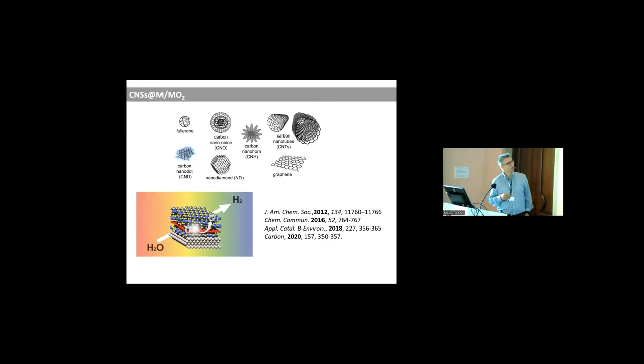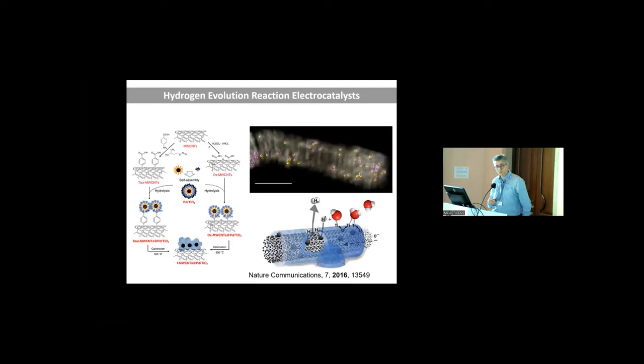Another part I want to emphasize is how important it is to mix materials together. And we love to combine our core shell strategy with different carbon nanostructures, different materials. Just to show you a third example, we use a palladium embedded titanium core shell material prepared in the same way as we did for cerium dioxide. And we were able to locate this catalyst at different distances from the surface of nanotubes. And we show how important it is to have the two components connected and talking to each other to minimize the overpotential we have to apply in the hydrogen evolution reaction.